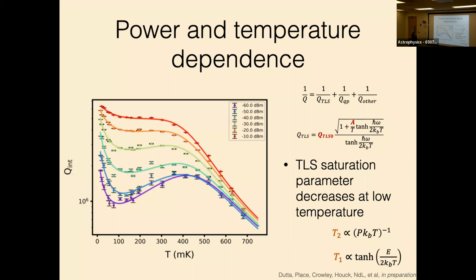And then we can write down a model that has losses associated with two-level systems, losses associated with equilibrium quasi-particles, that's basically this drop off here as you approach the critical temperature of the superconductor, and then something that sets a ceiling on all of this that's temperature and power independent. So with only like 6 free fitting parameters, we can fit this entire data set very beautifully.